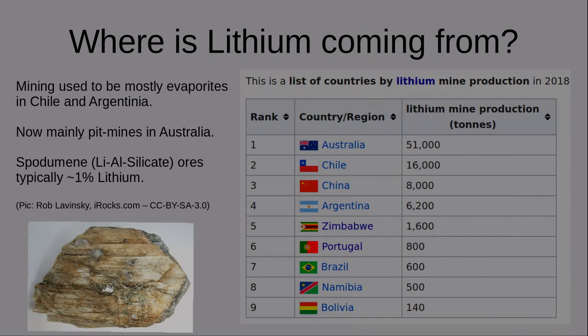Lithium. Where's lithium coming from? For years, I was always sure that most of the lithium is coming from Chile, and it's not too bad. I wasn't wrong, but actually, this changed in the last 2 years. These days, most of the lithium is coming from Australia. And what changed is that lithium used to be mined simply by pumping water into the ground, into salt layers where you had a lot of lithium salts, pumping the water up, evaporating it, concentrating it, and extracting the lithium from that. There are some spots where this is possible, and this is actually quite easy and also quite cheap. But that's limited, and we've pretty much run up to the limit.